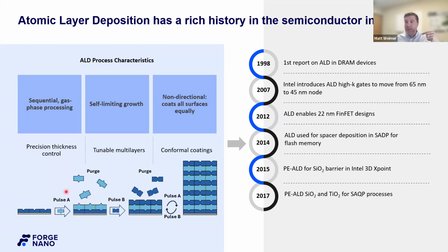Of course, now you have to remove all of these blue spikes. We call that the purge step. This is actually why ALD is so slow. You have to remove all of the precursor because you need two precursors. They have to be separated both in time and in space. They should never see each other. Also not shown here is a reaction byproduct. Sometimes that can really affect things, but not all the time. But let's keep it simple for now.